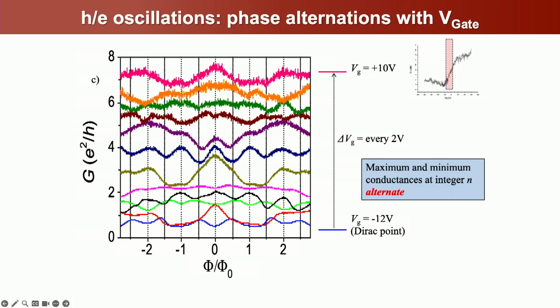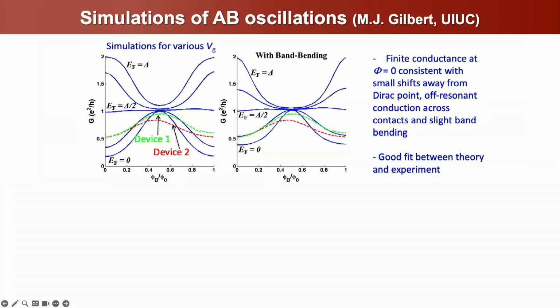Okay. So our theory collaborator Matthew Gilbert did some simulations of this and showed that, even though we don't actually have 0 conductance where you think there should be 0 conductance, that may be associated with a little bit of tunneling or co-tunneling across the contacts due to band bending. But overall, there's a good fit between theory and experiment.